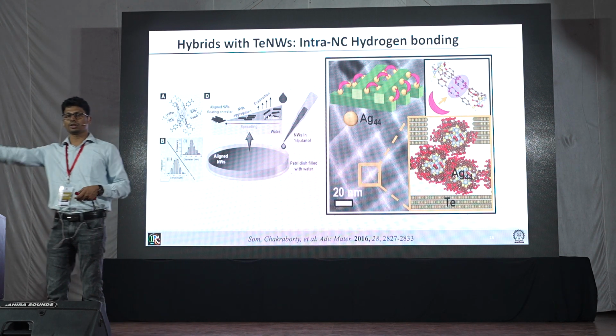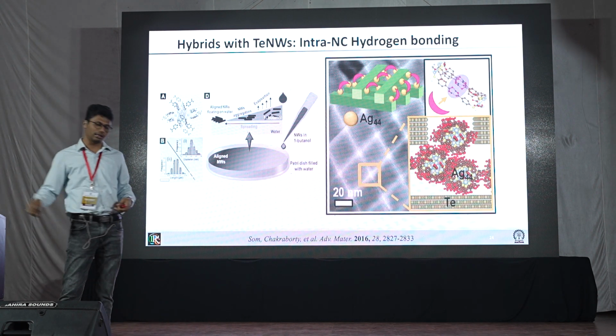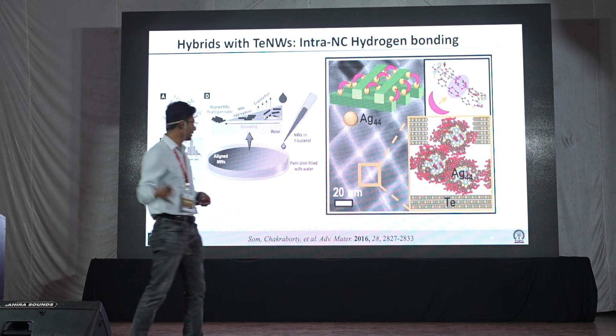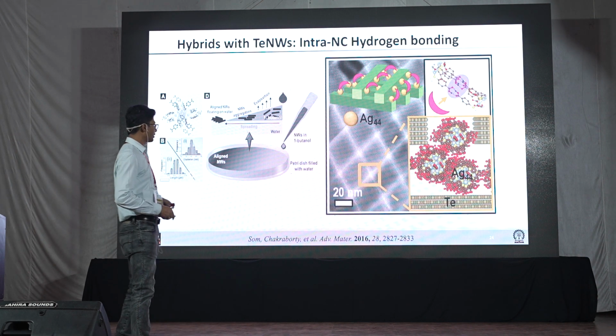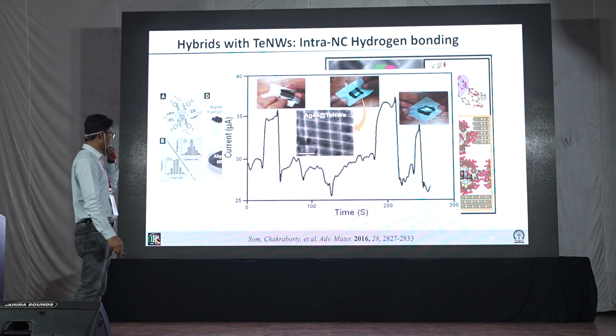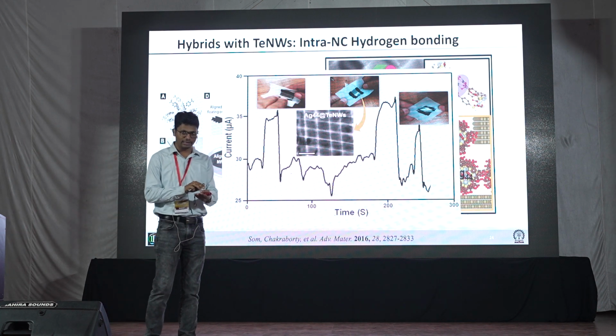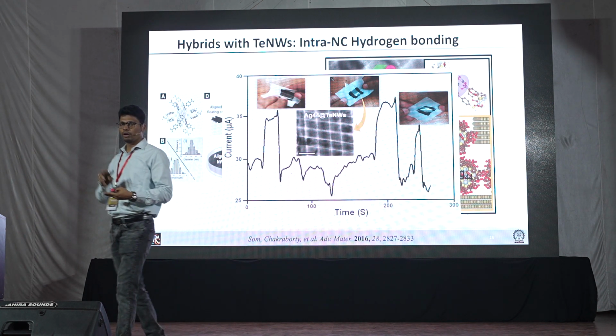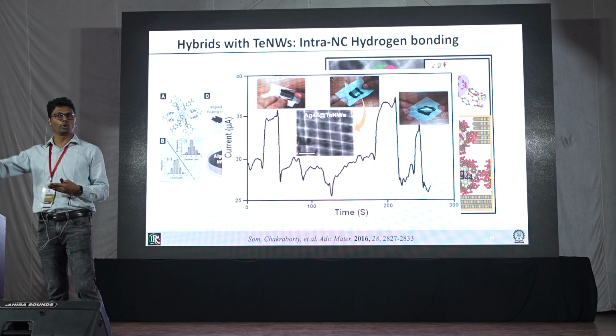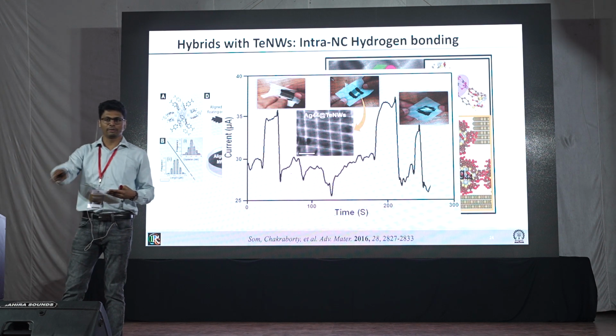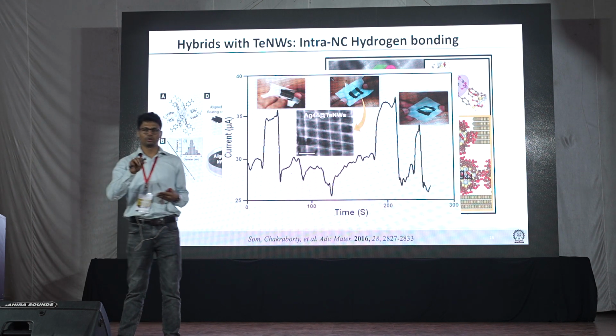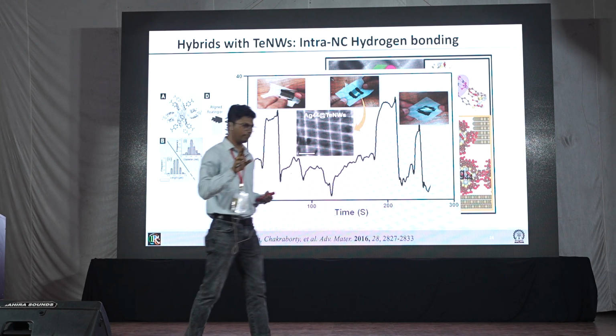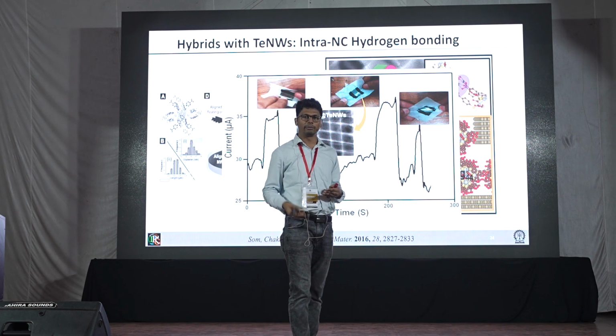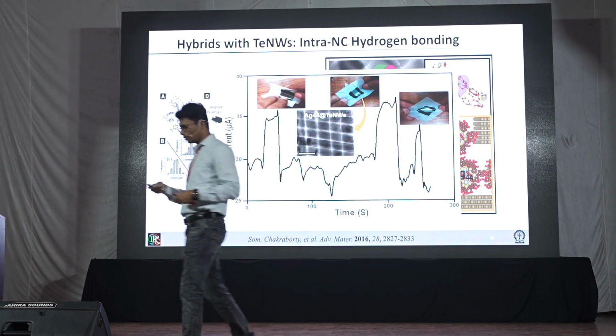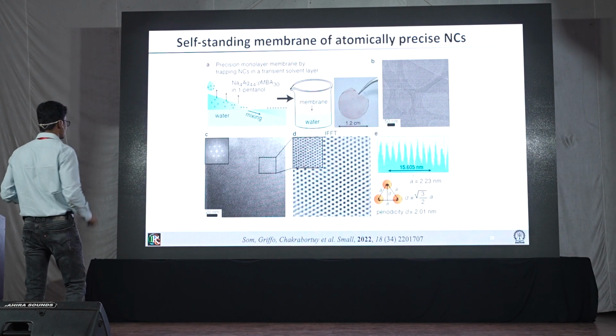Now, if you increase the concentration of clusters on top of tellurium nanowires, it forms bundles, and several other things we have carried out in that paper. If you're interested, you may look at that. And based on that, since they are strongly interconnected now in a bilayer, you can use them as a strain sensor. This is nothing to do with the cluster again. This is to do with tellurium because they are strongly connected. So if you just bend it, then you can get a response. And based on that, you can play around and make a strain sensor out of these things.